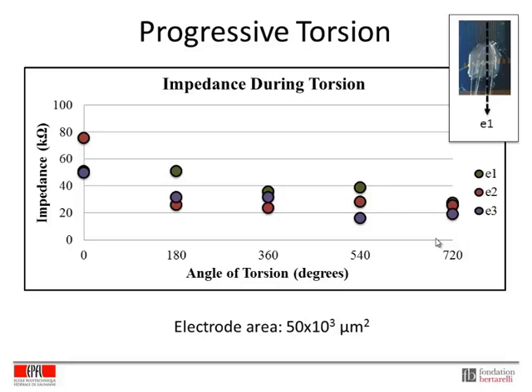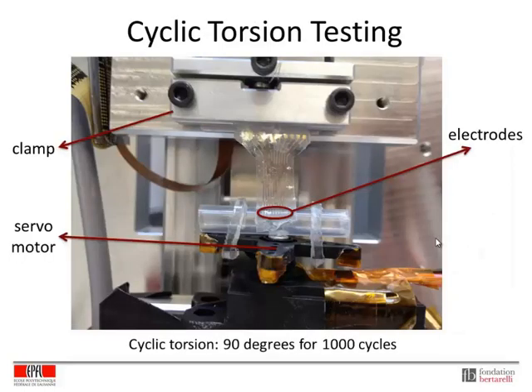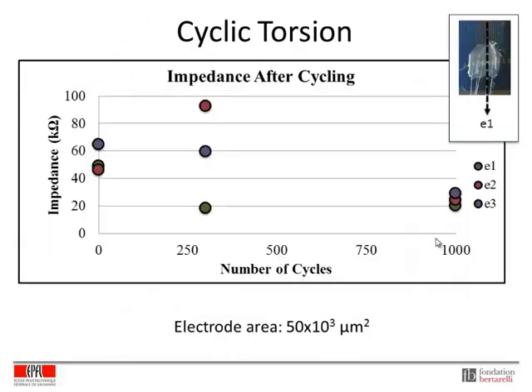Just to move along a little bit quickly, we did the same thing, but we did torsion testing over long-term cycling using a similar clamp attachment and a servo motor for torsion. And these were our results. Again, the electrode E1, which is in the center of the array, has the most stable impedance, whereas the other two are influenced by the other stretching components of the strain.